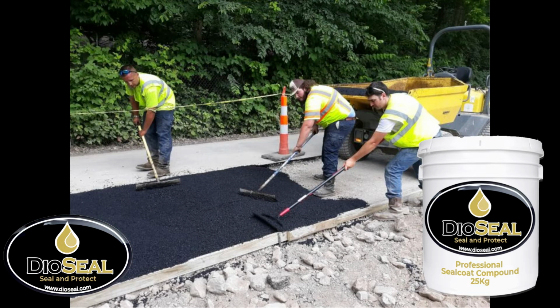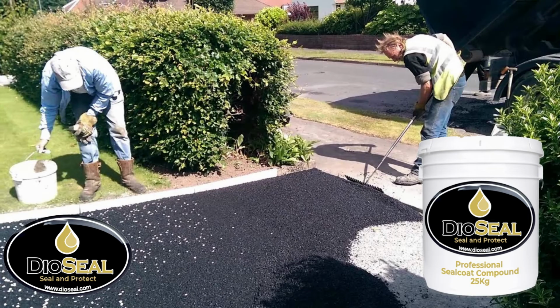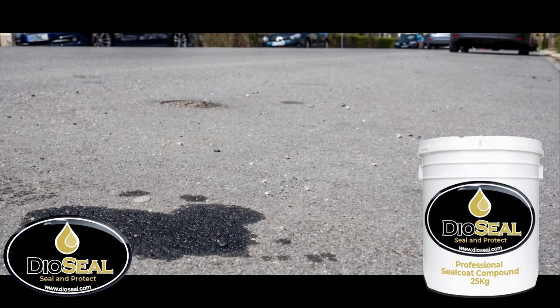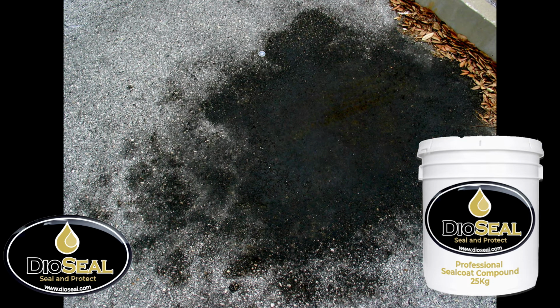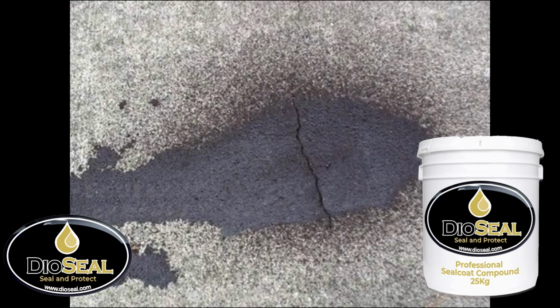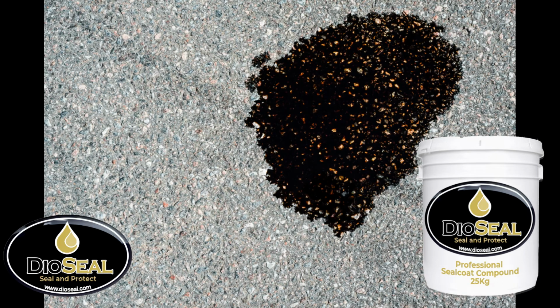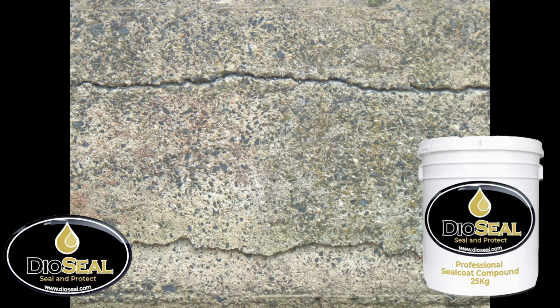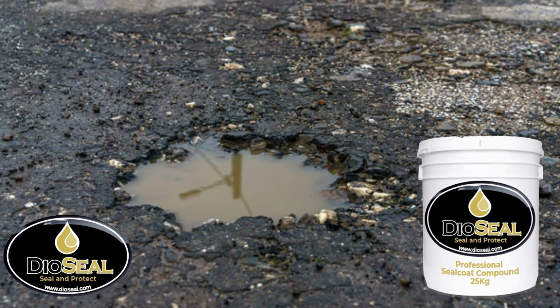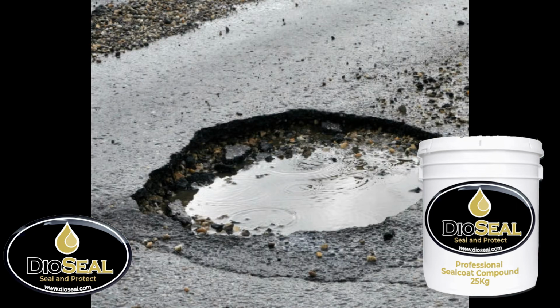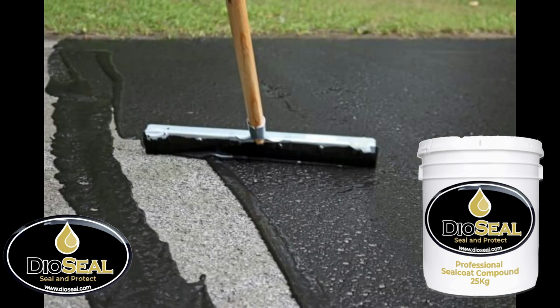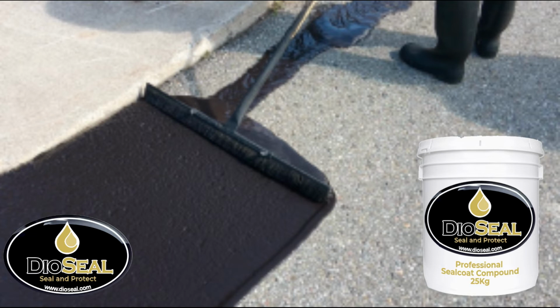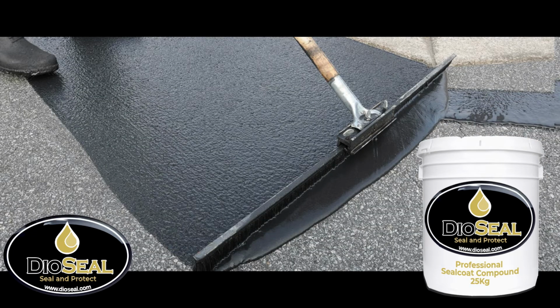Asphalt is generally made up of a blend of sand and gravel aggregate mixed with a petroleum-based binder that makes it flexible and pliable to make laying quick and easy. As motor oil and petrol leaks onto the asphalt, not only will it stain, it reacts with the petroleum binder and causes rapid deterioration of the asphalt. On top of that, water and UV rays dry out the asphalt. Soon, the asphalt that was once flexible enough to handle temperature fluctuations and the pressure of traffic becomes brittle and prone to cracking and crumbling. Applying DioSeal Sealcoat blocks the damaging oxidizing substances and keeps the binder pliant and flexible, allowing it to stay in good condition for a longer period.